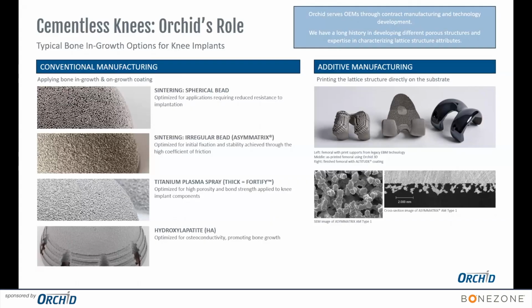Coatings using traditional sintering and plasma spray require a lot of masking so that the coating doesn't go in areas where you don't want it to go. That issue is completely eliminated when you do the 3D printing.